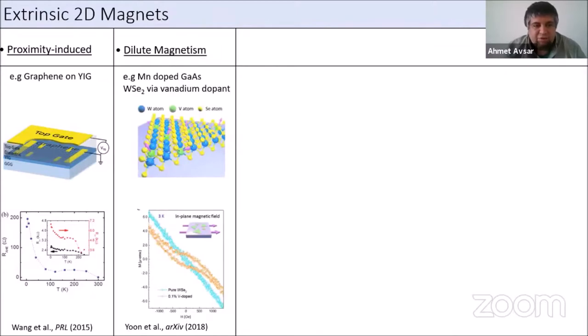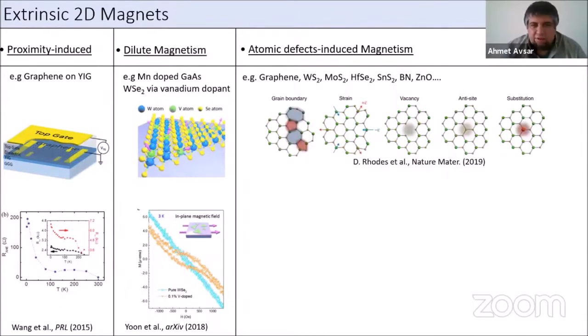Okay, and the second method is dilute magnetism. In this case, you put some other atoms on top of these materials, and then they turn into magnetic materials. You can, for instance, check manganese-doped gallium arsenide, or even 2D materials. Recently, it was shown that if you dope tungsten diselenide with vanadium, you can induce magnetism. And the third approach was defect-induced magnetism.